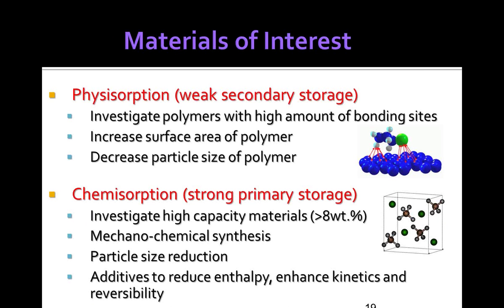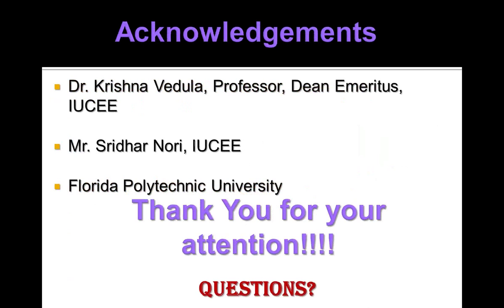This is the option of weakly bonded polymer nanostructures, increasing the surface area on polymer and decreasing particle size. Chemisorption of some complex materials like lithium magnesium compounds and using mechanochemical synthesis and particle size reduction. Additives to reduce the enthalpy and enhance the kinetics.